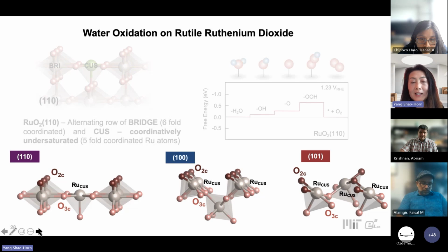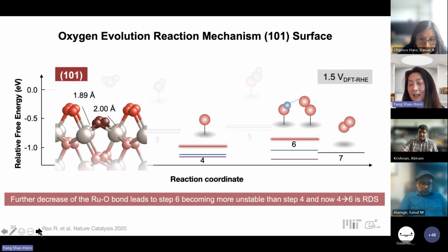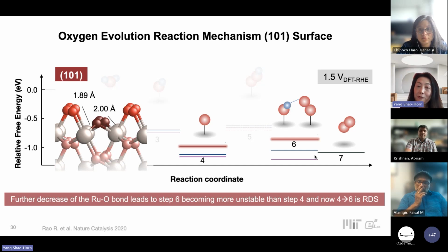And we performed measurements, and we note that if we have different CUS sites, from 110 to 100 to 101, we gradually weaken all oxygenated species. Right, so for 100, we weaken the species such that the deprotonation of the superoxide species reduces the barrier, and so 100 has much higher activity than the 110 surface. But if we further weaken all the species, then the prior step, the conversion of O to OOH, becomes rate limiting, and then the catalytic activity of 101 is reduced.